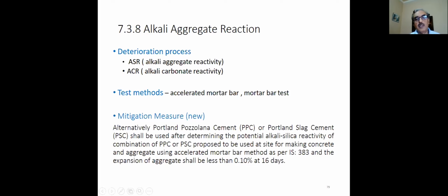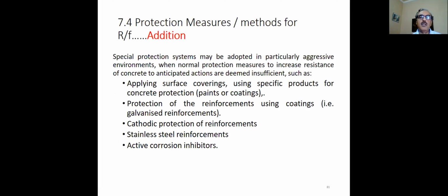And there are test methods to again verify. So what we can do is not only standard testing, we can use the proposed PPC and PSC and do a test. If the expansions are within limits at 16 days, if it is less than 0.1%, we can use that. So these are some of the changes made. It is a kind of updation, nothing major as such.